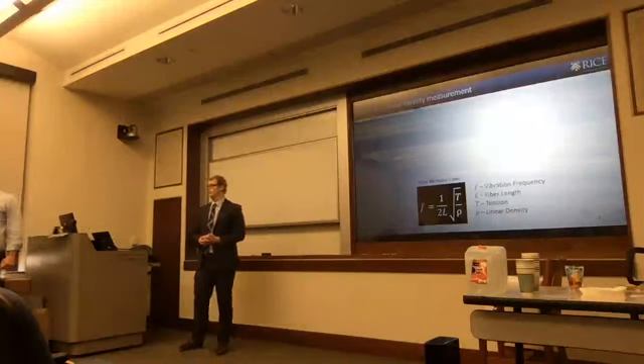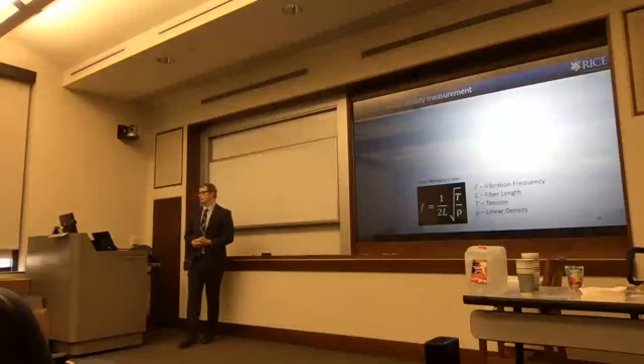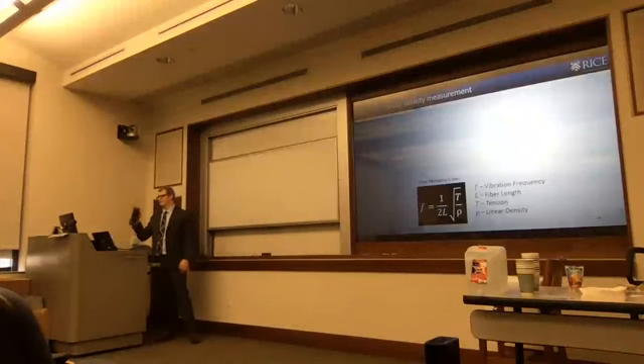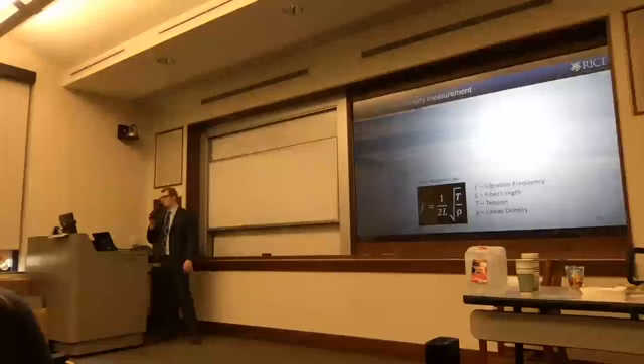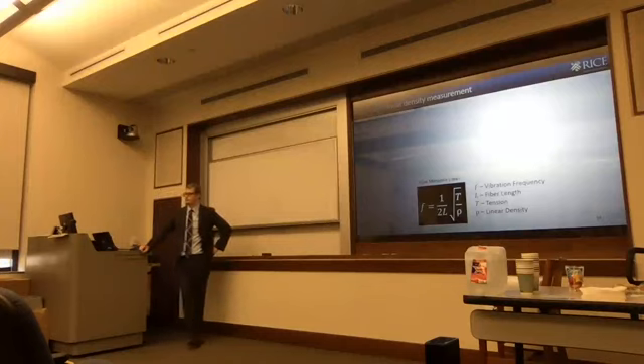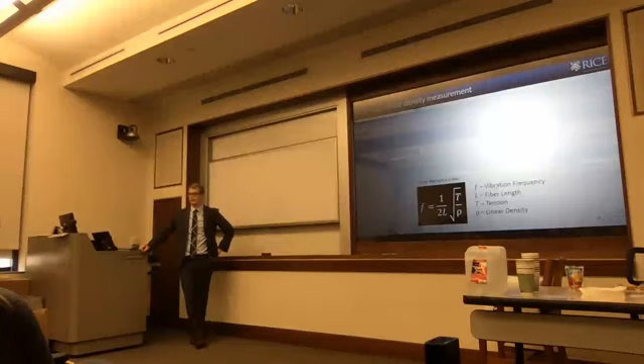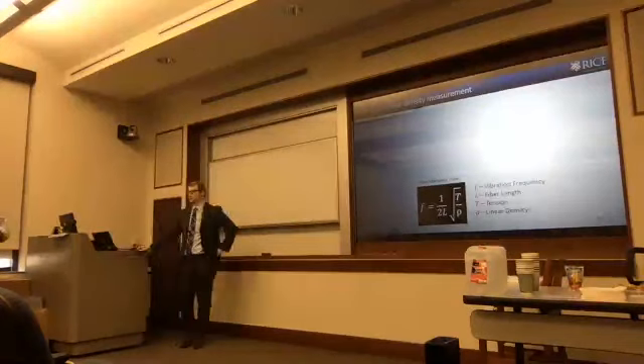On the same vein, does this relationship account for, is it measuring the linear density of an untensioned and unelongated fiber, or, along Matteo's question earlier in the talk, you're getting a bunch of linear densities as you go. Are those accounting for the change in the linear density? Because if you stretch a fiber with the linear density not going down, it just doesn't matter. Sure, and that trend actually is opposite of what you would expect, because the lower frequencies correspond to the lower diameter.